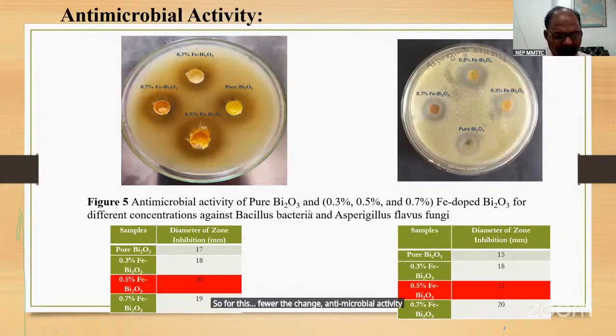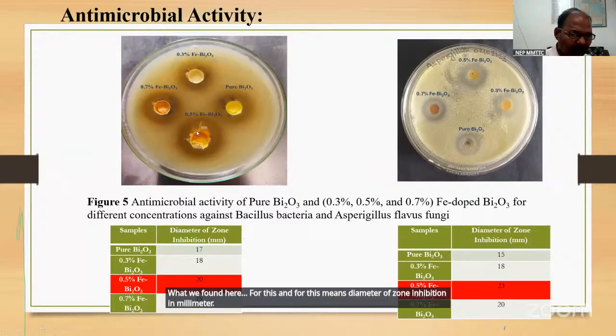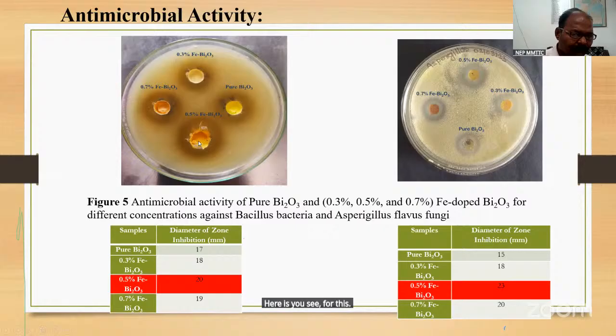Antimicrobial activity of pure and iron doped Bi2O3 against bacillus bacteria and aspergillus flavus fungi. Okay, this is the fungi where 0.5% iron doped Bi2O3. Here the diameter of zone of inhibition, what we found for this, is in millimeter. Here you see for this 0.5%, too much. Okay, so these are the